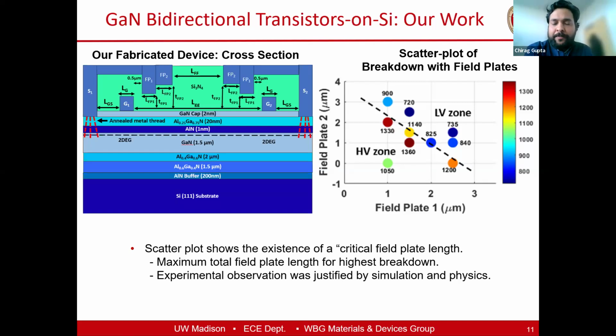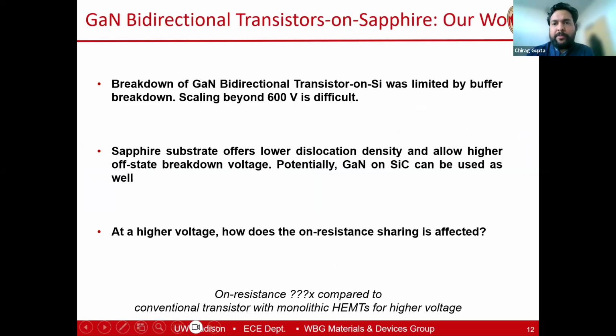And for that, we had a whole array of different field plate 1, field plate 2 designs, and one has to take into account the fact that there might be some alignment errors. But what we saw was if we had our field plates slightly on the shorter side, it helped in managing the peak fields better. And we saw something similar with the TCAD simulations as well. So nothing too out of the ordinary, and these numbers were comparable with state of the art.